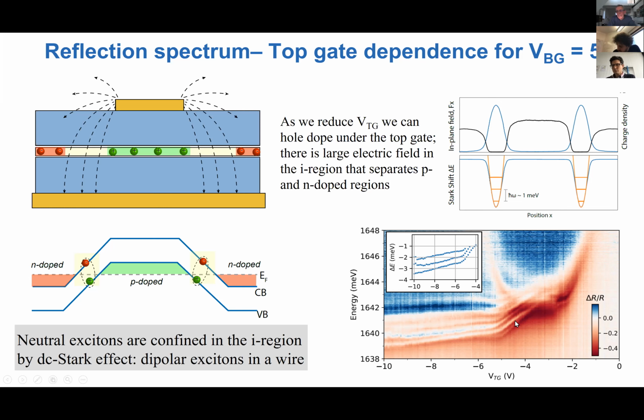And we believe that these are essentially quantized, one-dimensional excitonic states that exist only in the region in between the two layers. Okay, so it's really remarkable that this confinement, particularly for these lower energy states, is in large part due to the DC Stark effect. But you can see that there are even confined states with higher energy than the exciton, and we believe that this is due to the fact that the repulsive polaron formation in N and P doped regions essentially contributes to confining the excitons in the undoped region.